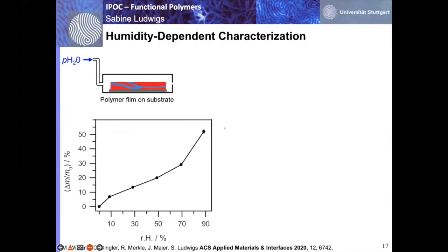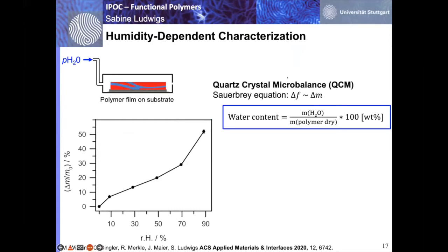And taking now these PEDOT:PSS films, and using the so-called method of quartz crystal microbalance, QCM, and by using in these regimes the Sauerbrey equation, where we get frequencies out and related to the mass, we can actually calculate the water content in the film. So when we take such a PEDOT:PSS film, as I said, it's this kind of self-assembled morphology. The blue phase is the polyelectrolyte phase, and this material takes up water, and you see here that's a dry state at 0% relative humidity, and that would be 90% relative humidity. So we have here 50% water uptake in the film. So the film is also increasing in film thickness, because it takes up the water. So we can reliably determine the water uptake.